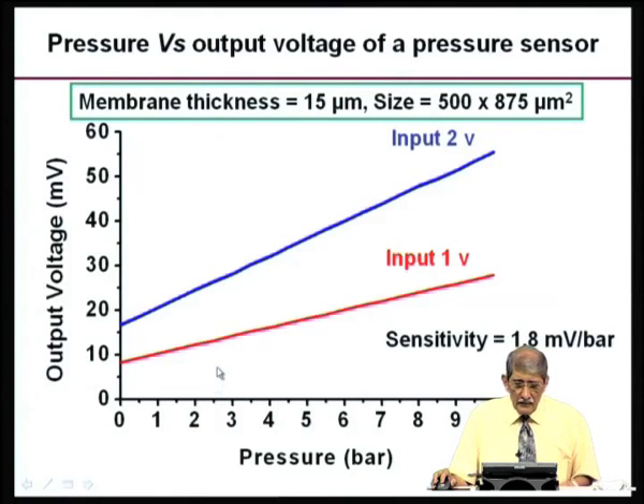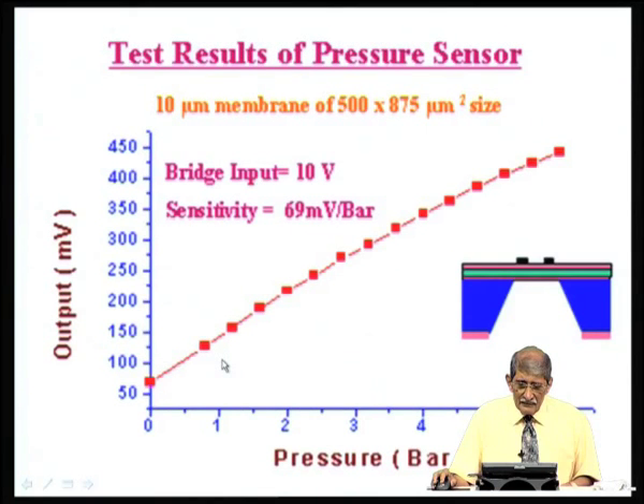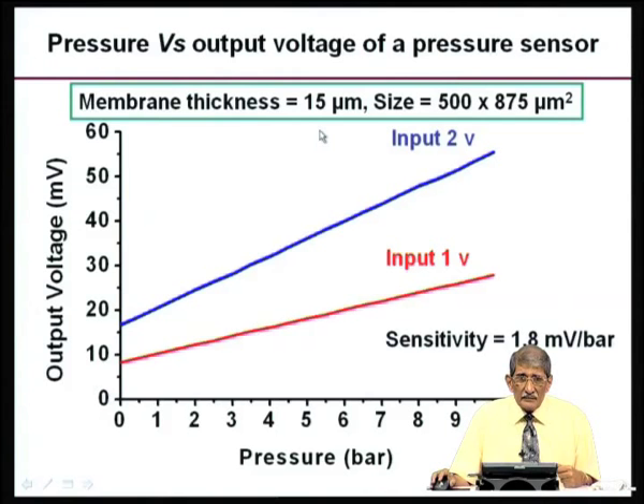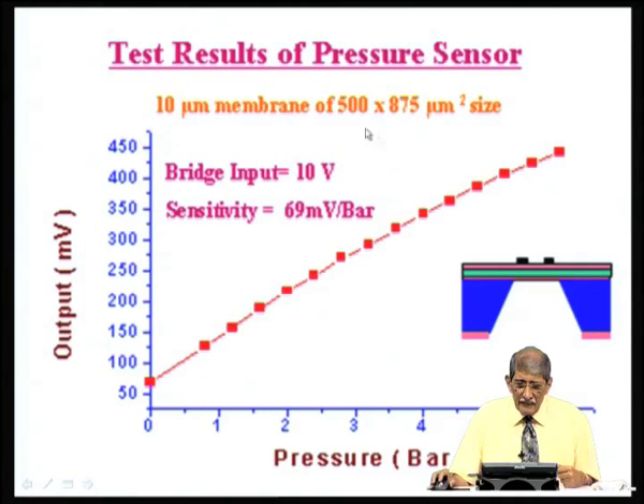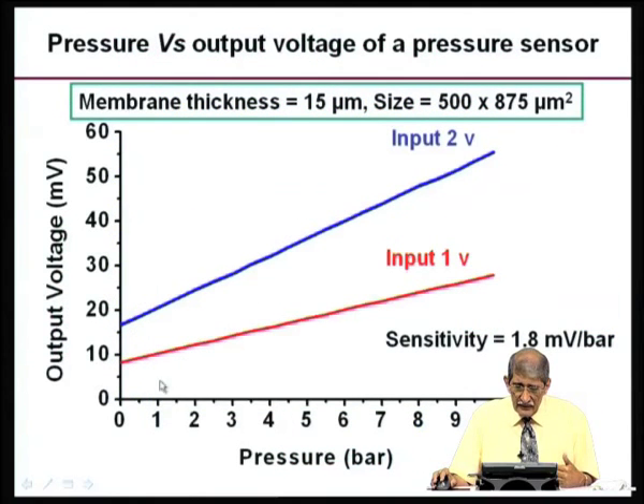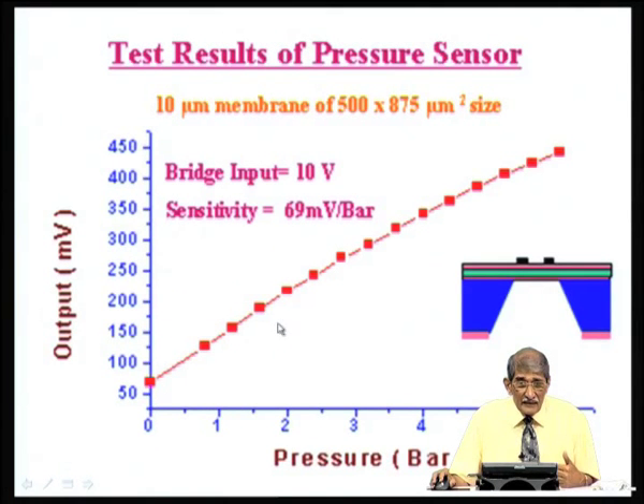Okay. Now, let us see this. See, this is a 15 micron thick membrane. If I make the thickness less, 10 micron, you can see that output sensitivity goes up. For 10 volts, it is 69 millivolts, that is for 1 volt, it is 6.9 millivolts. In the previous case, for 1 volt, it was 1.8 millivolts. The sensitivity is better because thickness is smaller, deflection is more.